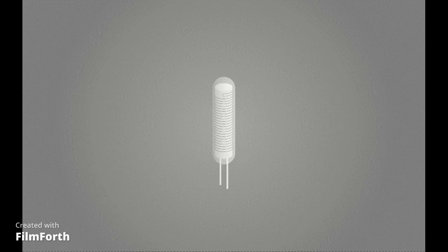Wire wound RTDs start out with a glass or ceramic core around which the RTD metal wire is wound. After connecting wires are attached to the RTD, the whole thing is encased in glass or ceramic. Wire wound RTDs are vulnerable to shock and vibration, but have better accuracy and stability than thin film RTDs. The glass encased type can be immersed in water, but is limited to temperatures below 400 degrees centigrade. The ceramic encased type can be used from minus 200 up to 650 degrees centigrade, or up to 850 degrees centigrade with special construction, albeit with reduced accuracy.